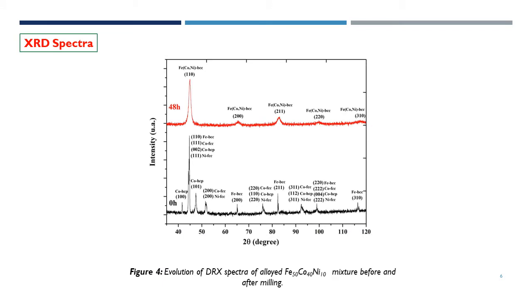As established by the X-ray diffraction analysis, an iron-cobalt-nickel BCC solid solution has been formed after 48 hours of milling. This new phase was promoted by the diffusion of cobalt and nickel atoms toward the BCC iron structure. Only peaks belonging to the iron BCC structure can be identified as the milling time increases up to 48 hours, confirming the formation of the solid solution inside the iron matrix.